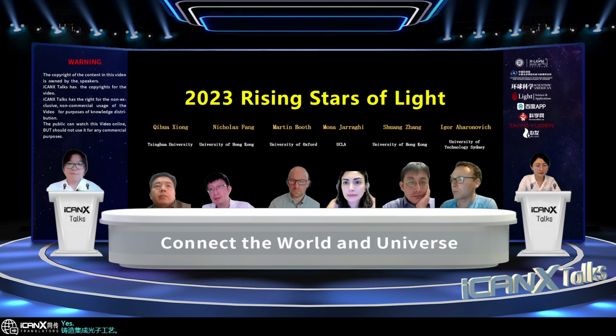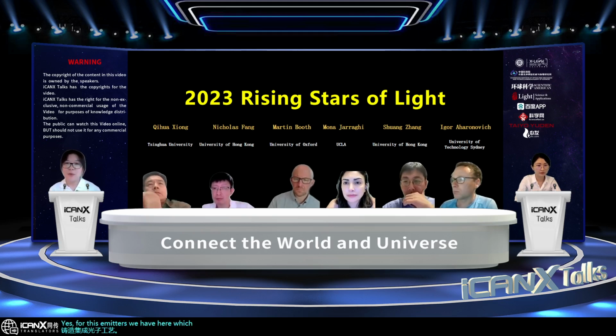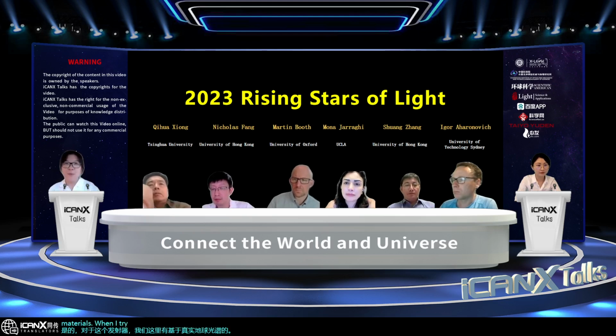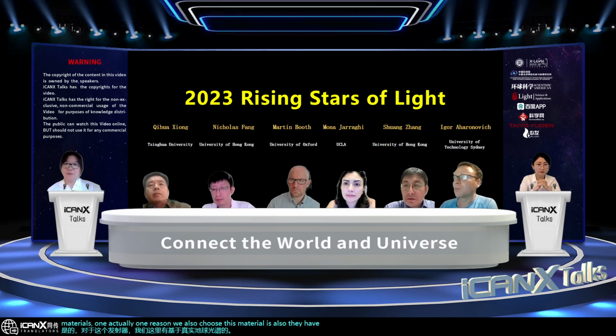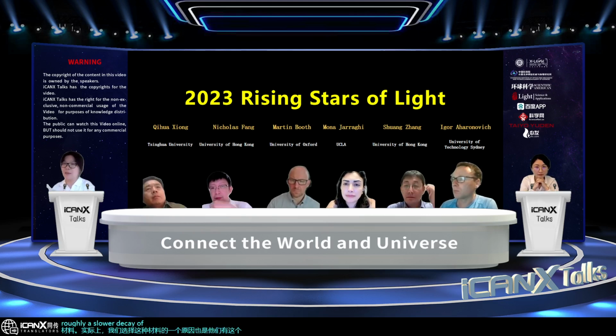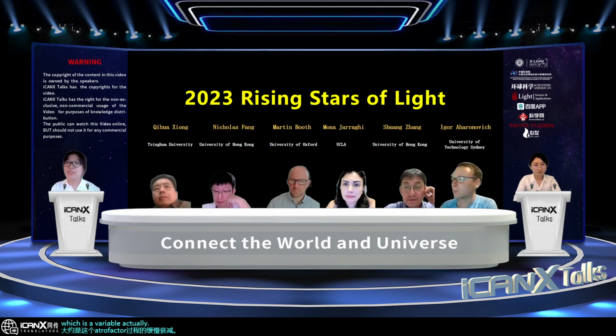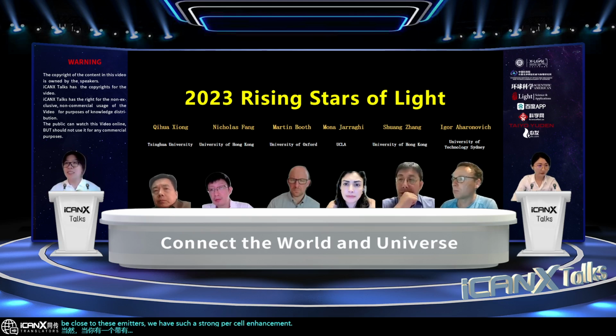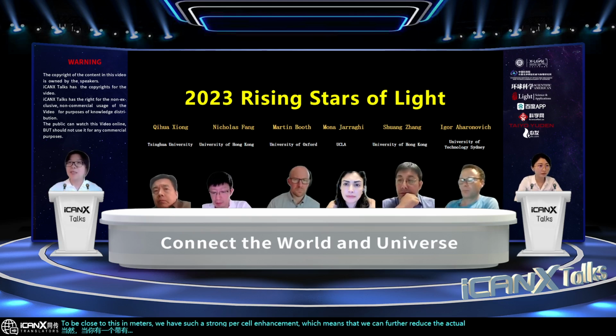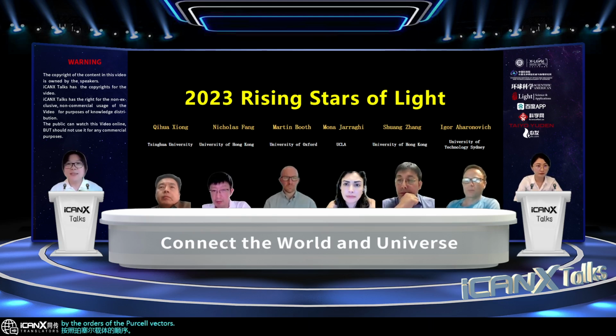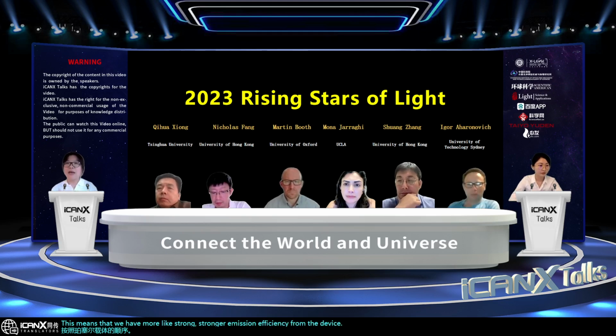Yes, for these emitters we have here, which are based on rare earth materials, one reason we choose this material is that they have a roughly slower decay than ultra-fast processes, which is favorable to continuous wave pump. Definitely, when you have a cavity close to these emitters, we have such a strong Purcell enhancement, which means that we can further reduce the decay lifetimes by orders of the Purcell factor. This means that we have stronger emission efficiency from the device, and also more ultra-fast modulation in principle compared to emitters that are bare in air.